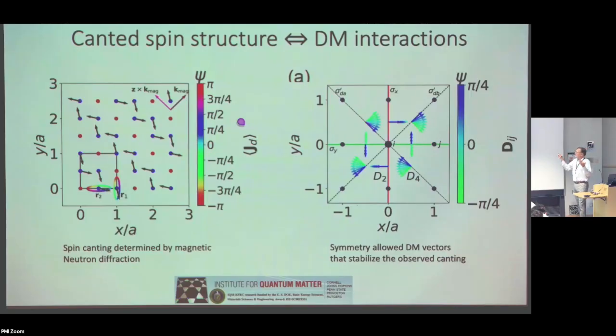And Chris took another step, which was that he tried to really pin down the Dzyaloshinskii-Moriya interactions as well. And this was done by measuring this little canted component of the spin structure that I mentioned, the fact that the spins are rocking back and forth. It turns out that they're not just rocking back and forth in a direction perpendicular to the wave vector, but they actually have this particular structure. This is an experimental result taken from magnetic neutron diffraction. All of these angles and so on have been determined by Chris experimentally.